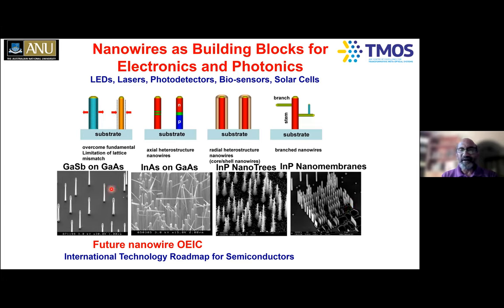be grown on top of gallium arsenide despite large lattice mismatch, we're able to show that you can make atomically perfect gallium antimonide on top of gallium arsenide. You can create branched nanowires, which could be very useful for cantilevers and also scanning probes. Also, we created indium phosphide nano trees, which are very good for energy harvesting applications like splitting water to generate hydrogen as a clean energy source. And also indium phosphide nanowires, too, where nowadays we're moving towards membranes rather than just nanowires, which I'll come back and share with you.